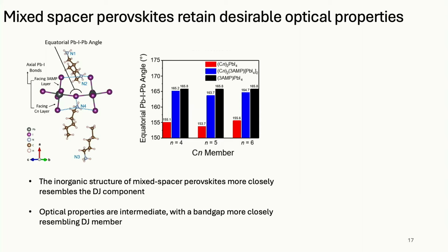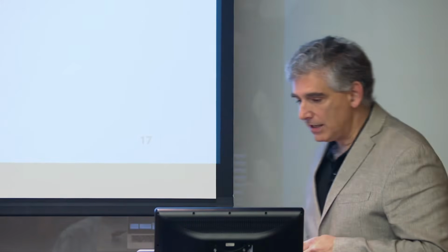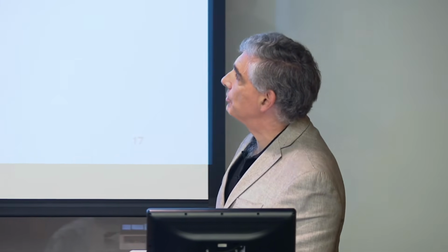Okay, and so now what are the structural properties? So if you look at these octahedra, we're always asking questions about how much do the octahedra tilt. So this angle is very representative of that parameter. And so if you make it only with butyl ammonium, you get a much smaller angle. They're very tilted octahedra. And then if you do it only with the 3-AMP, they're much less tilted. They're closer to 180, which would be untilted. And it turns out that when you have both spacers, the angle is very close to the Dion-Jacobson. So we might hope that we're getting the favorable optoelectronics of the Dion-Jacobson end member. And then we calculated the absorption properties.